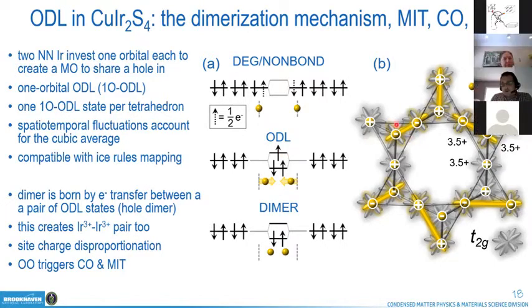Interestingly enough, because this is highly randomized, each iridium has 6 neighbors to make this state with. Through spatial and temporal fluctuations, this averages out to the cubic structure observed crystallographically. Another interesting aspect is if you take one orbital state per tetrahedron, you can exactly map it onto the ice rules. This is not a proof, just a conceptual cartoon.